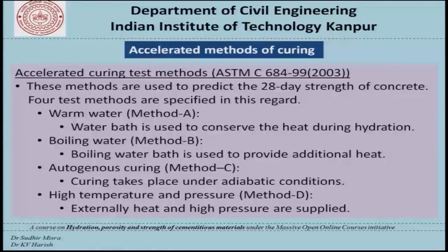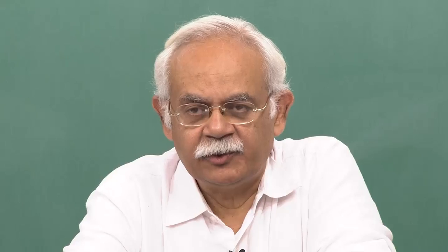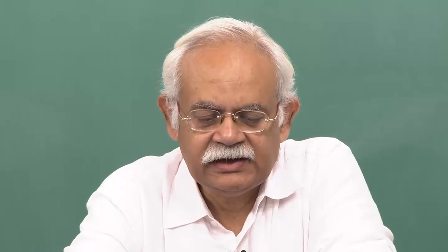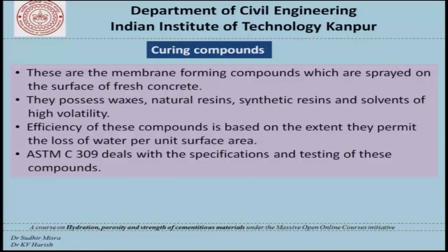Then there is another method of curing which has emerged, and that is the application of curing compounds. These are membrane forming compounds which are sprayed on the surface of fresh concrete. They possess waxes, natural resins, synthetic resins, and solvents of high volatility, and essentially form a membrane of their own by sealing the pores of the concrete at the surface.